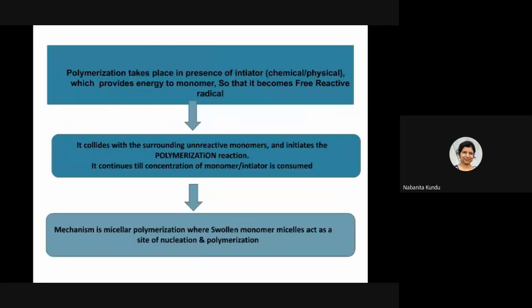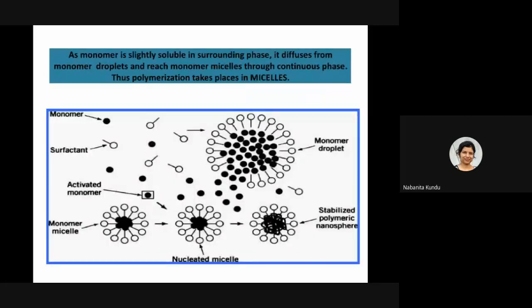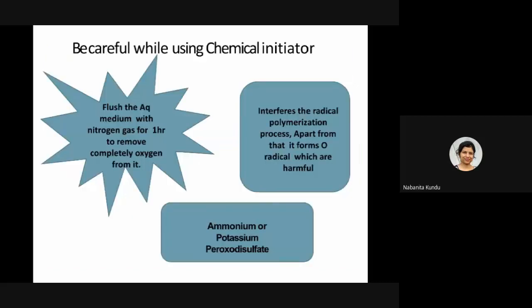the micelles. And finally, these are the micelles, you see monomer droplets and the emulsifier, they form those micelles, and there you have that polymerization going on. And once the polymerization is complete, you have to add some salt to break the micelles and precipitate your polymer. So that is the way, and this emulsion polymerization is the most common technique which is being used for polymerizing from monomers, right?